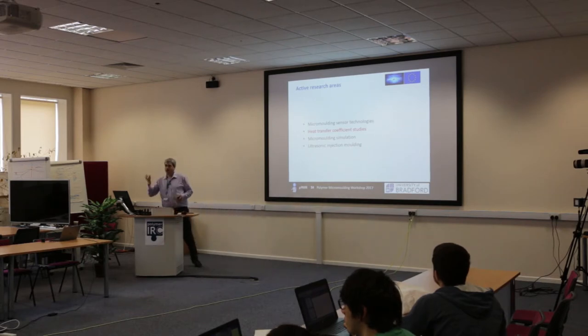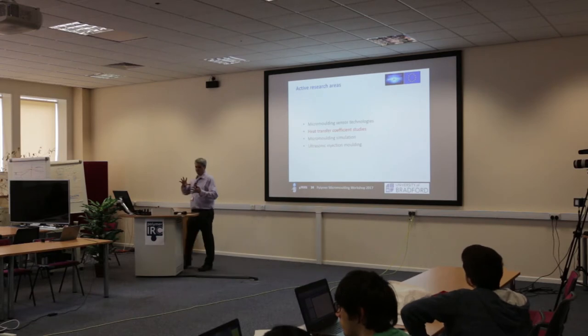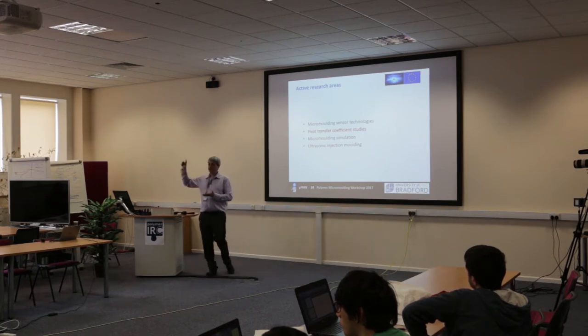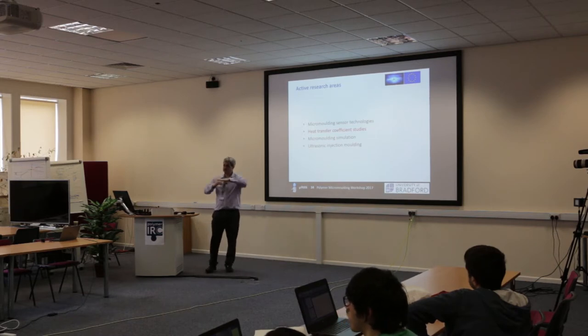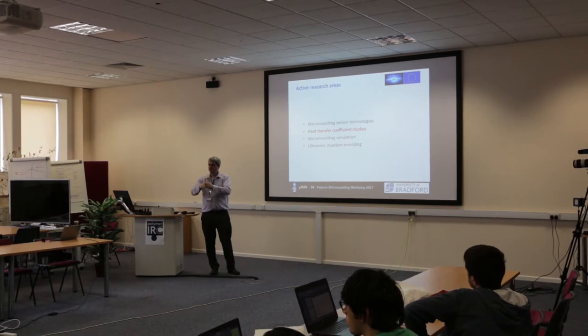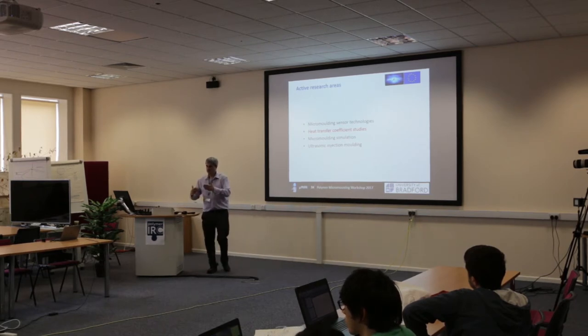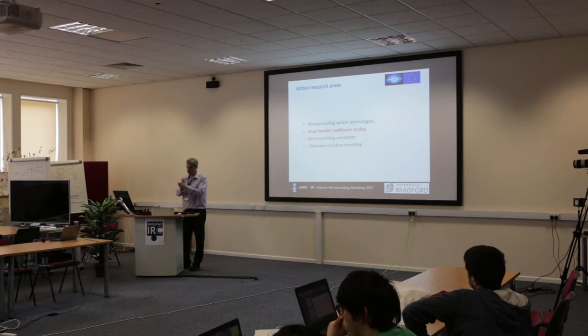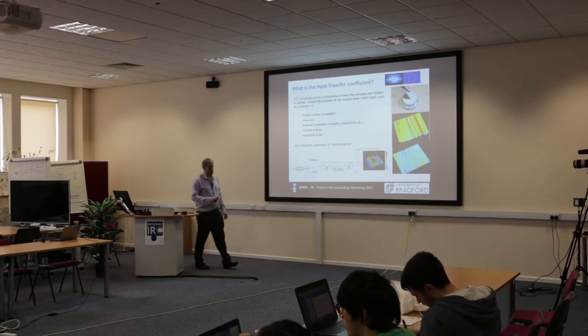These measurement capabilities allow us to measure something crucial for micro injection molding. Things get more difficult as we move to smaller components — one main reason is that as you reduce part size, its surface area to volume ratio increases significantly. In a micro-scale mold, more of the material is in the near-wall region — the interface between the melt and the steel becomes hugely significant. Most of the material is in that near-wall region, so cooling rates are much higher than in conventional injection molding, and heat transfer across that boundary hugely influences overall cooling, morphology development, and resulting physical properties.